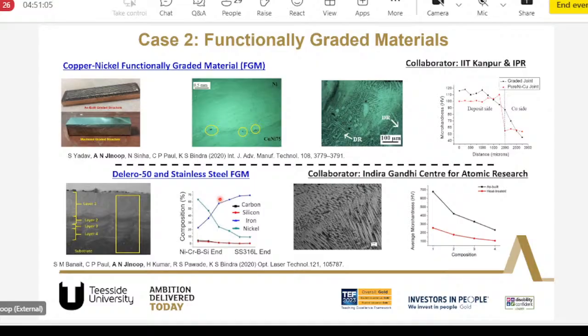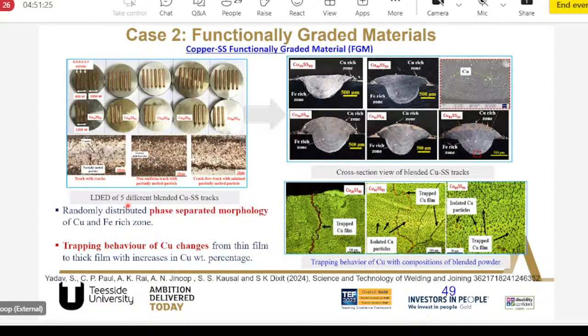In this case, we had copper and nickel change. In this case, we had a variation from Delero, which is a nickel-based alloy, to stainless steel. So we pre-mix the powder in advance, then we deposit layer by layer with different compositions, and then we get these structures. Then one of the recent works that we did was on copper and stainless steel FGMs, where we varied the composition of copper and stainless steel.